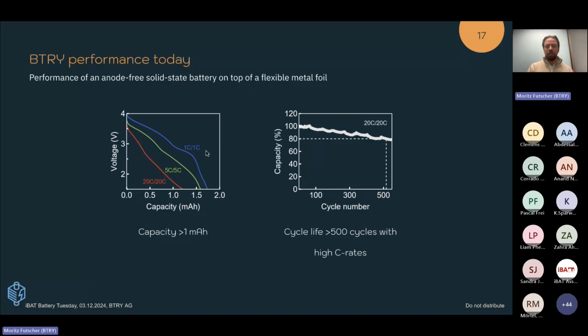So you see different C rates, and on the right you see the cycling performance of one of these cells. If we cycle this at 20 C, both charge and discharge, meaning just 3 minutes charging, 3 minutes discharging. And this over several hundred cycles. In this case, we showed above 500 cycles. And this is something which is already not easily possible with classical lithium-ion batteries, but also not with solid-state batteries.